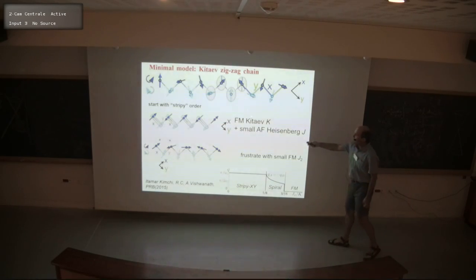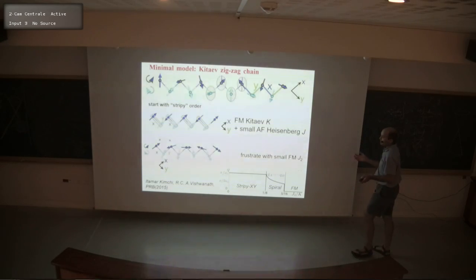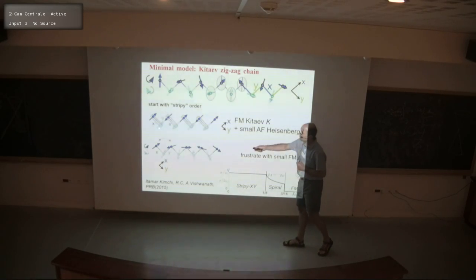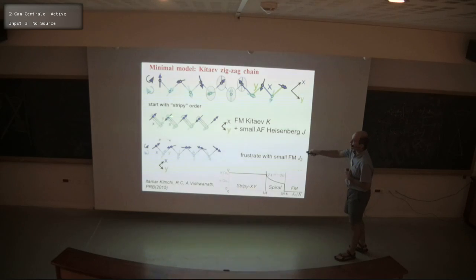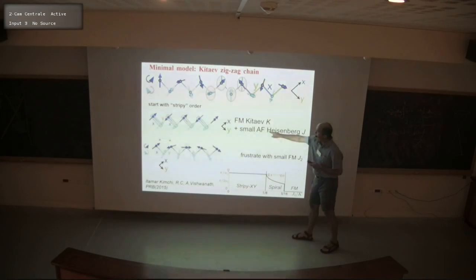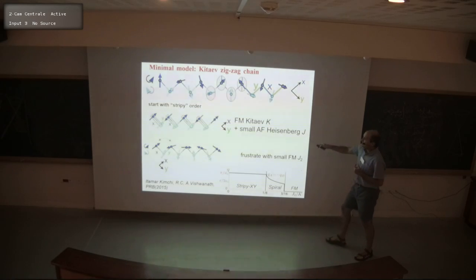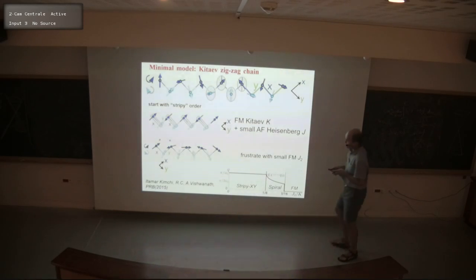So imagine that we have a Kitaev exchange on the zigzag chain. So the best you can do is to put ferromagnetic dimers. And then you have a choice how you put it between neighboring dimers. And so if we have a small antiferromagnetic exchange, then we make this dimer anti-parallel to the first one. And so the structure alternates like this.